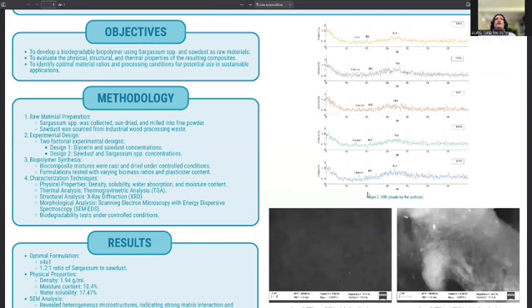Finally, we did the characterization techniques. We measured density, moisture content, water solubility, and water absorption. Thermal stability was analyzed via thermogravimetric analysis (TGA). Structural properties were assessed using X-ray diffraction (XRD), while the surface morphology was observed under scanning electron microscopy with energy dispersive spectroscopy (SEM-EDS). Finally, biodegradability was tested under controlled conditions.